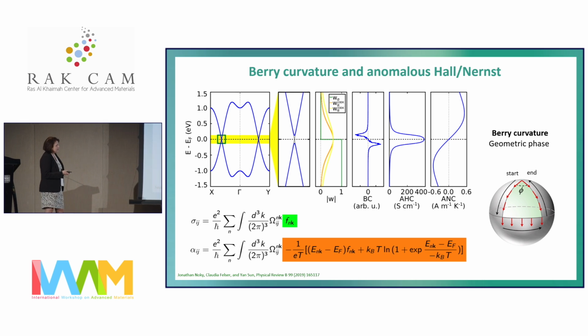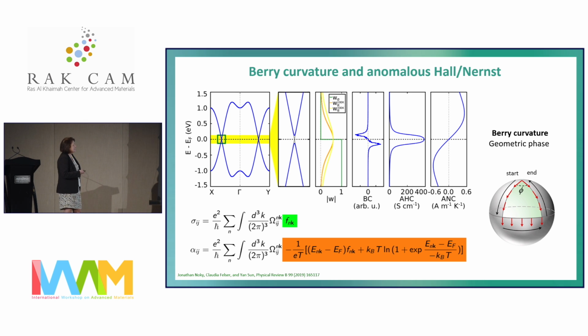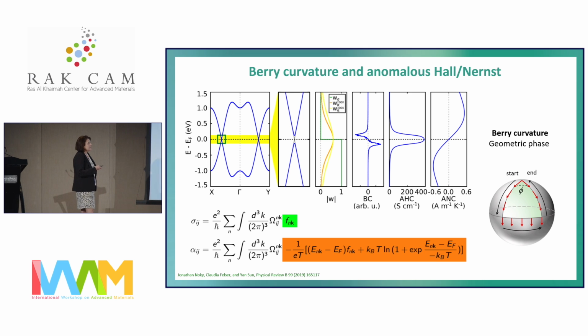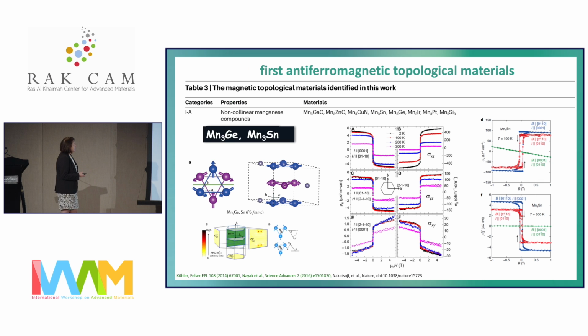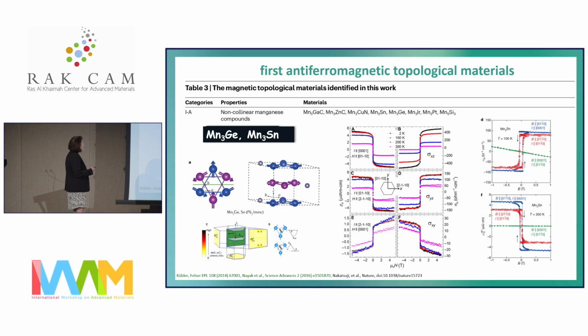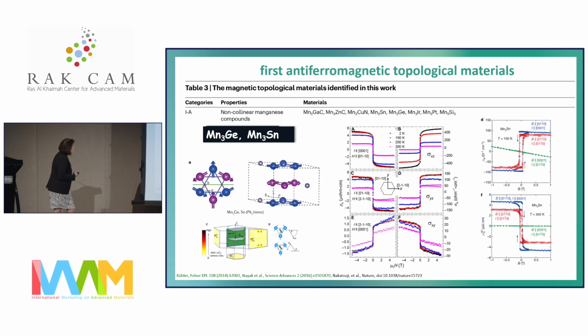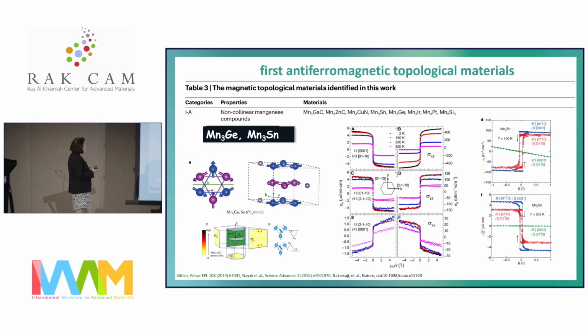But then people like Naoto Nagaosa already developed the theory, and they recognized that certain features in the electronic structure, like crossing points, for example, can lead to an enhancement of the anomalous Hall conductivity and the anomalous Nernst effect. So now, how can we find interesting material? And indeed, at this time, when we looked for frustrated magnetism in the antiferromagnetic manganese-3 germanium and manganese-3 tin, again with Jürgen Kübler, we found out that even though these are antiferromagnets and they have no net magnetic moment, they had a giant Hall effect, a giant Berry phase.